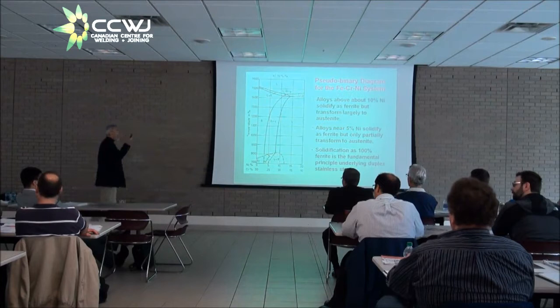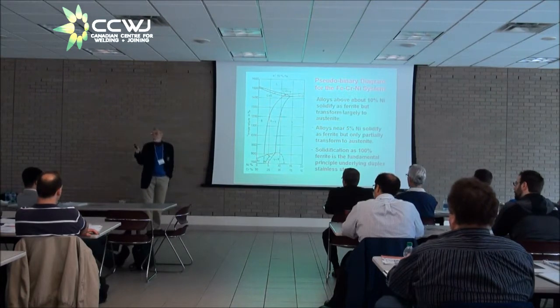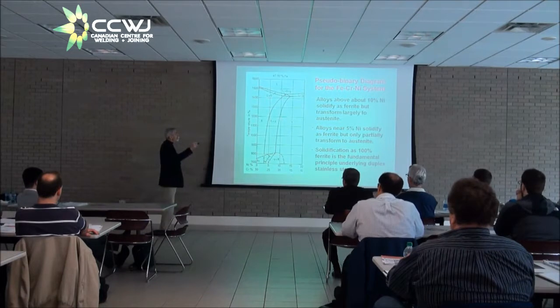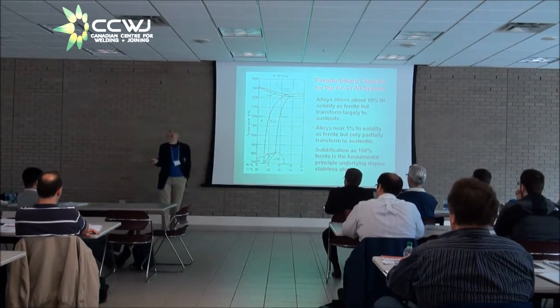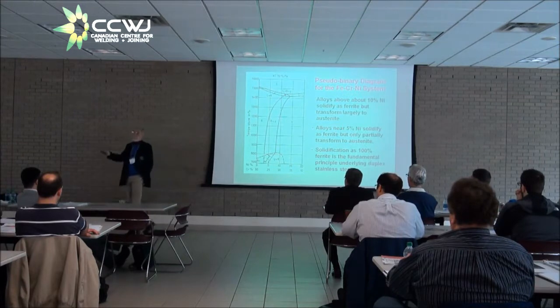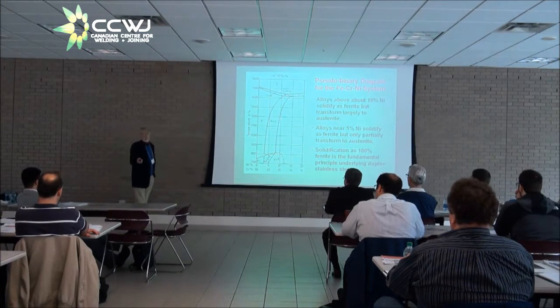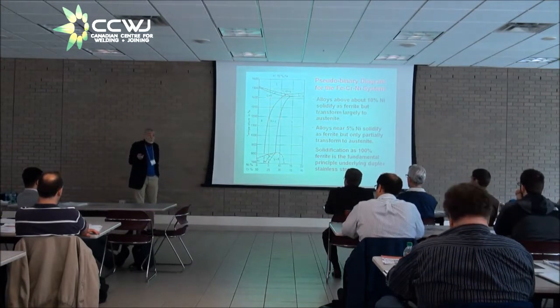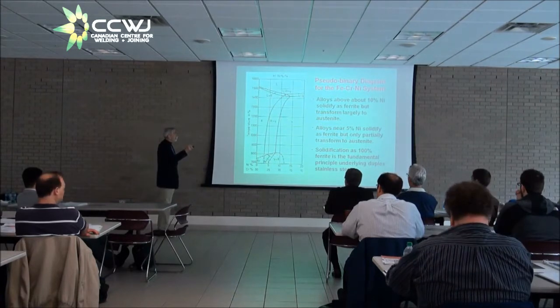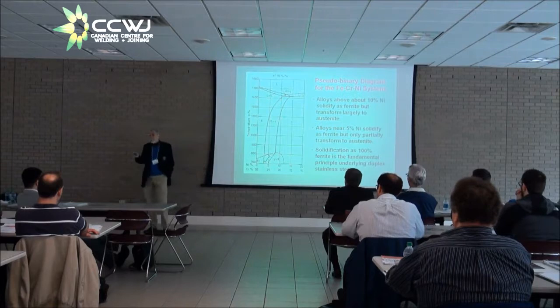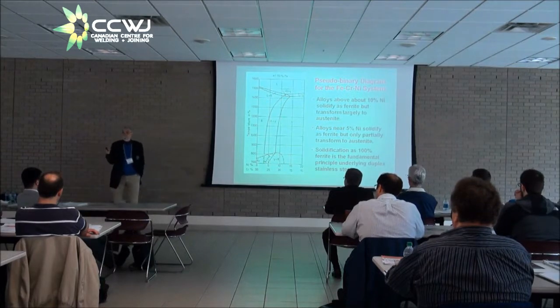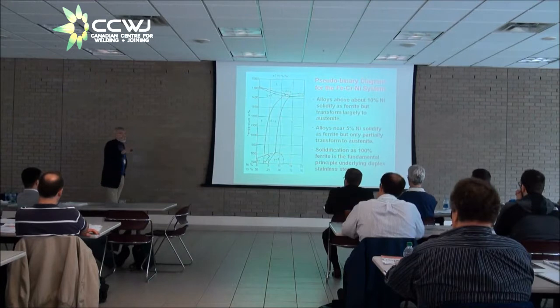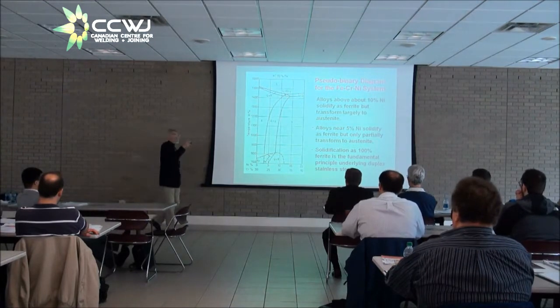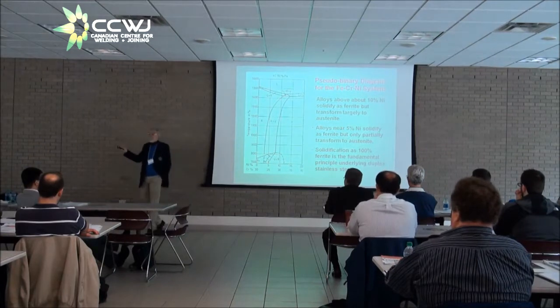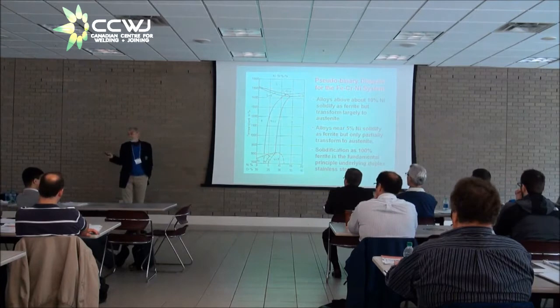Now, how easily the austenite forms depends upon how high the temperature is when the first austenite forms. If the first austenite forms at a high temperature, then diffusion is pretty rapid. Chromium can partition to the ferrite, nickel can partition to the austenite, and it's not very dependent upon cooling. But if the first austenite doesn't show up until a rather low temperature, now the diffusion of chromium and nickel is very limited. The end result is that you don't partition chromium and nickel. And that's where you can get into some trouble with these things, because you're locking in very high ferrite. You don't get anywhere near equilibrium transformation of austenite, and the end result is you get very poor mechanical properties.